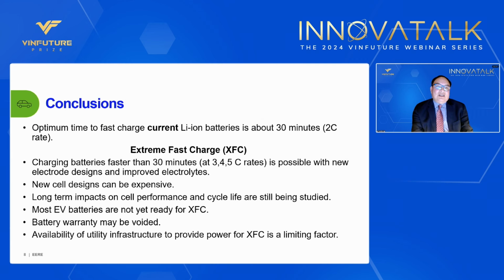So in summary, the optimum time to fast charge current lithium-ion batteries is about 30 minutes or so, roughly about 2C rate. Charging a battery faster than 30 minutes, at 3, 4, or 5C rates, we consider as extreme fast charge. It's possible with new electrode designs and improved electrolyte.